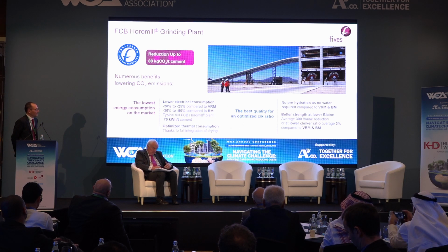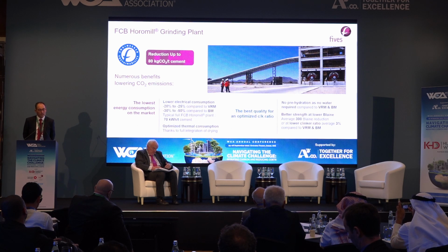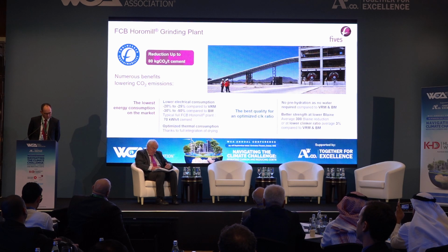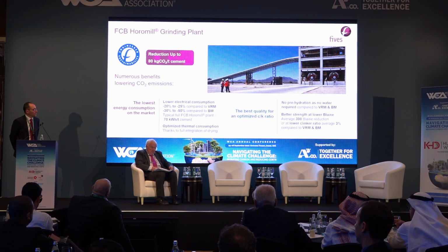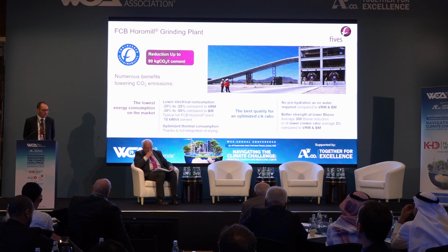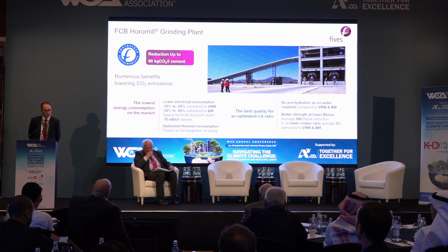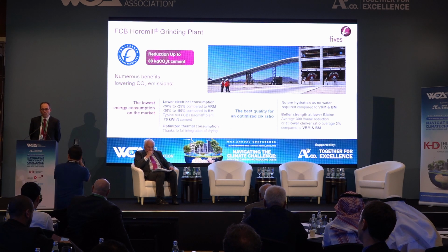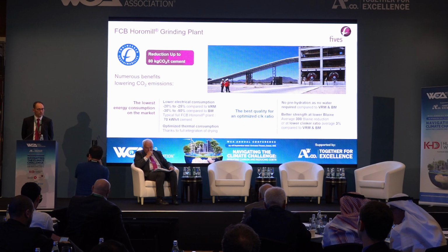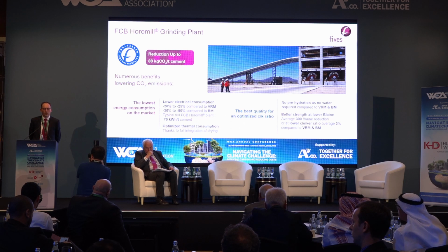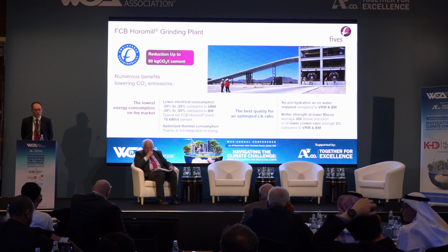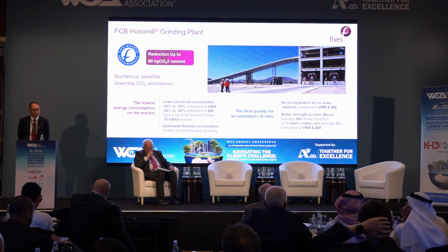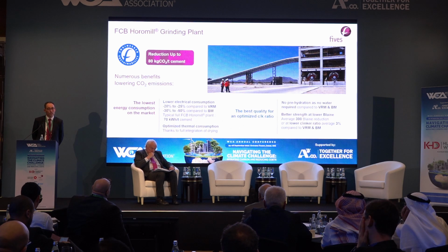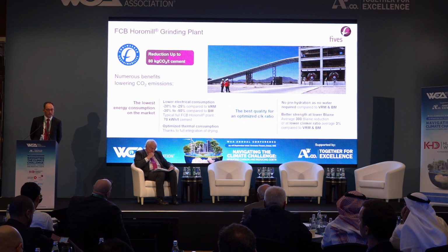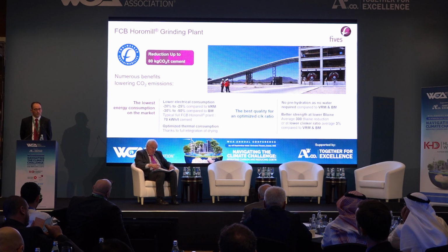And the thermal consumption as well has an effect on the energy, because the drying of this mill is made to be very effective and limit the energy consumption from the thermal point of view. The second main family is the quality of your cement, and the goal here is to optimize the cement to clinker ratio, or the clinker factor. It depends on the region we are talking about. The goal being to substitute as much clinker as possible with alternative material. Without going to the calcined clay, we already achieve a cement to clinker factor equal to 1.8 in the Philippines using pozzolana and fly ash, which is very interesting in terms of CO2 emissions.